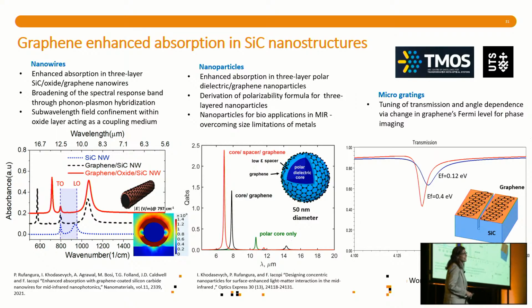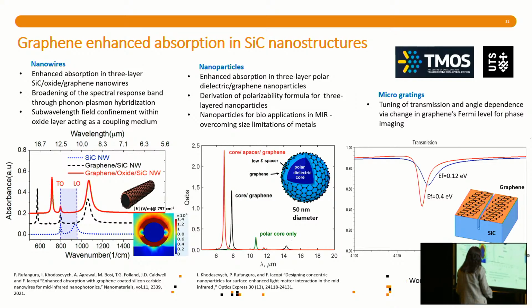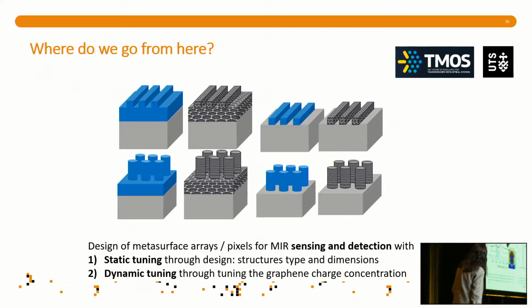And then we're working on microgratings, again made of silicon carbide, covered by graphene, for different types of filters. In this case, we are looking at phase imaging, just to manipulate the numerical aperture of a system directly using the physical filter. So these are some of the most important areas that we're working on at the moment. And this is all available thanks to the fact that this platform is very versatile. You can imagine that if you had to make any of these complicated structures by transferring, also because these are 3D, they're not just flat, you can't just put it on top of it. And they have high adhesion as well. So at the moment, this is one of the most straightforward ways of making that, and it gives you a lot of liberty. And then, of course, the long-term goal is to work on the dynamic tuning of the system.